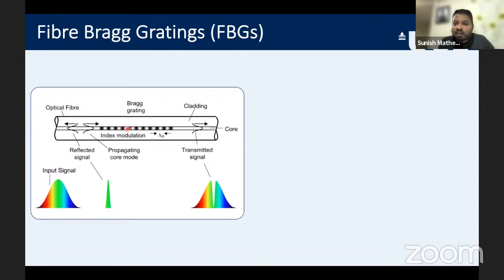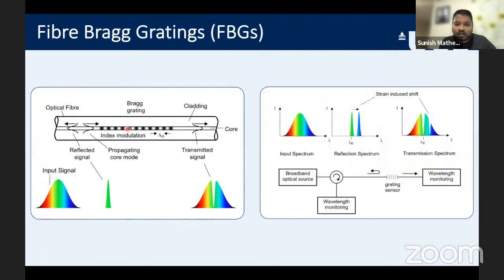And this kind of sensor is very sensitive to changes in strain or temperature. So when the temperature changes or the pressure changes, there is a shift in this reflected Bragg wavelength. And if you can detect this change in the Bragg wavelength, you can calibrate your sensor to the pressure or the strain that is causing this wavelength shift.